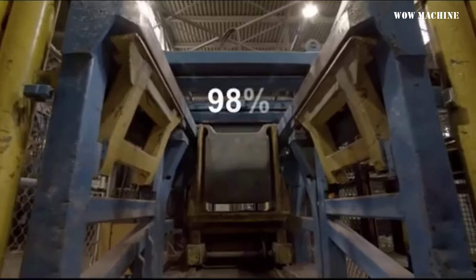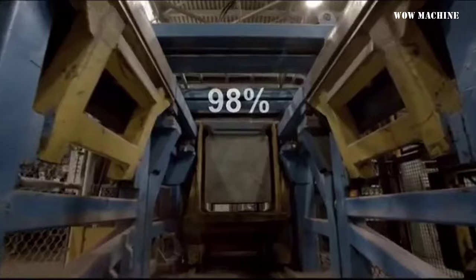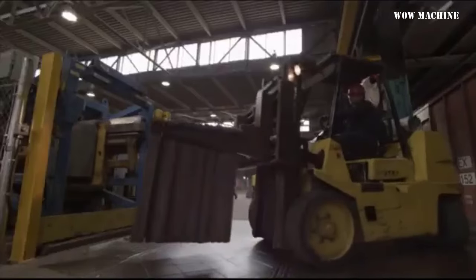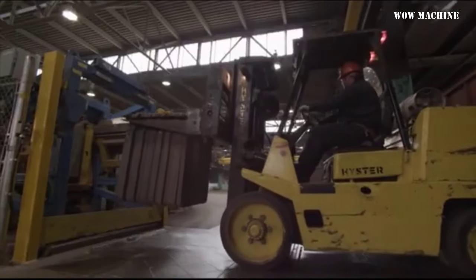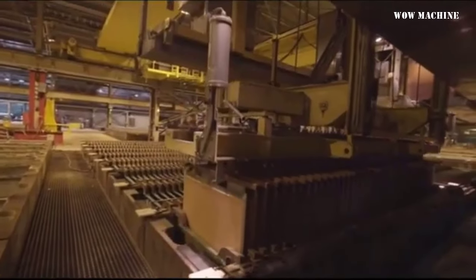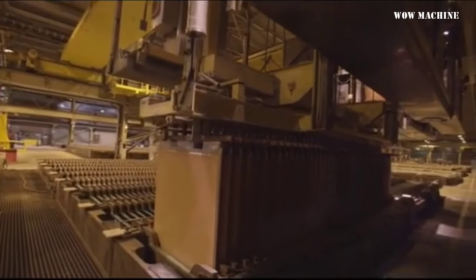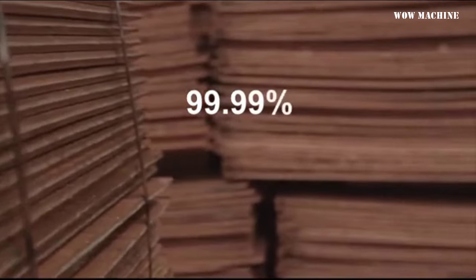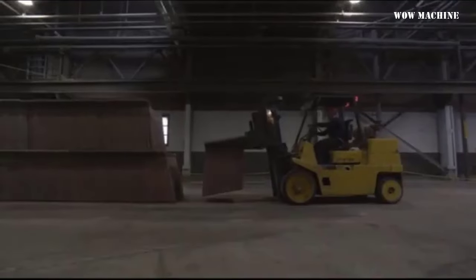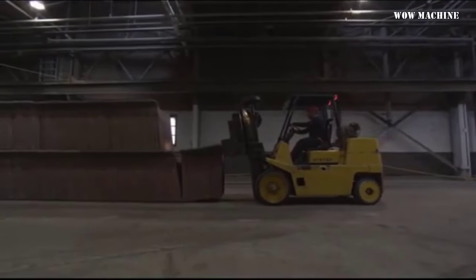At CCR Refinery, copper arrives with an average purity of 98%, whether extracted or derived from recycled products. However, this copper must undergo treatment to remove precious metals and chemical compounds, which are extracted during the refining process. Through this treatment, the copper attains a purity level of 99.99%.